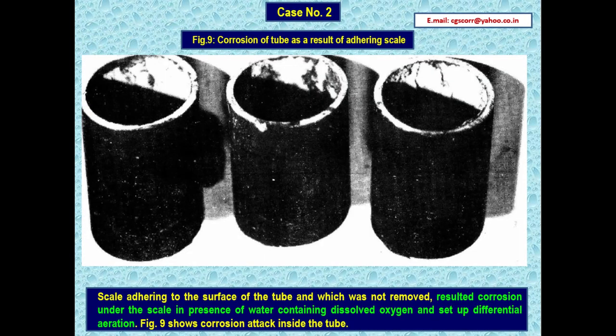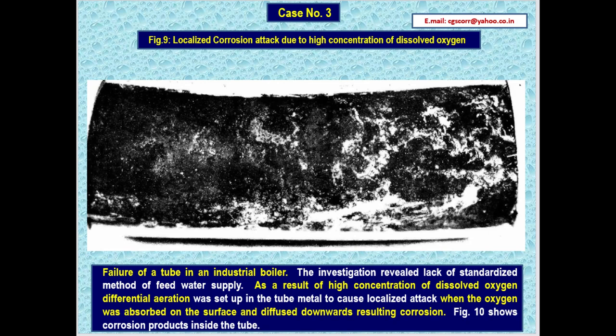Figure 9 shows the corrosion of a tube as a result of adhering scale. The scale adhering to the surface of the tube, which was not removed, resulted in corrosion under the scale in the presence of water containing dissolved oxygen and set up differential aeration. Again, this figure depicts a localized corrosion attack due to high concentration of dissolved oxygen.